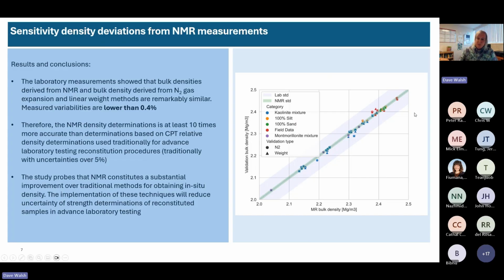So what you see here on the right is just a bunch of different samples that have been used to estimate the bulk density from the NMR measurement and compared to other methods like gravimetric measurements in the lab. And so that tight green spread there, that's the standard deviation or the variance of using in situ NMR to estimate density, versus this purple line, that's the traditional method of using just CPT alone and then follow-on laboratory work. So that's a big difference in the uncertainty of that particular method.